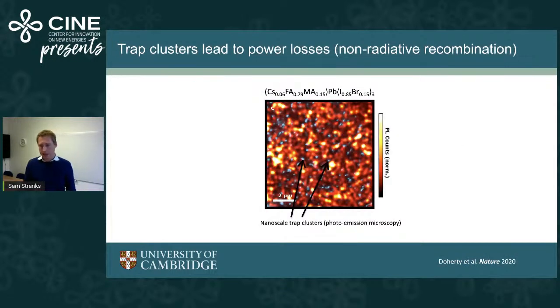So we can overlay this PEM or photoemission map, which shows the traps. This is shown in blue here with a photoluminescence map, and that's shown in this black to yellow to white color scale. And what you can see is there's quite a strong anti-correlation between this, particularly the darkest regions really have lots of these trap states. So in blue, these are the trap states. So this shows that these trap clusters are really very much responsible for the non-radiative recombination and non-radiative power losses that we're seeing in these solar cells.